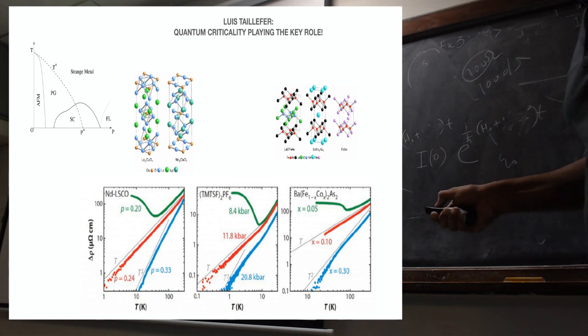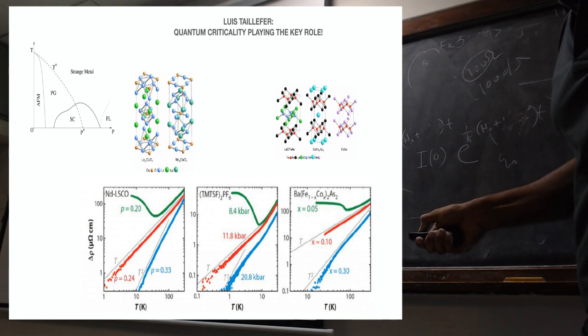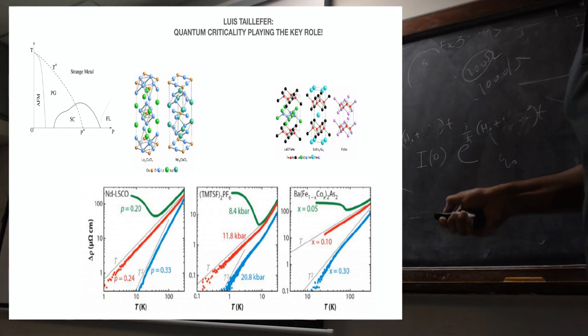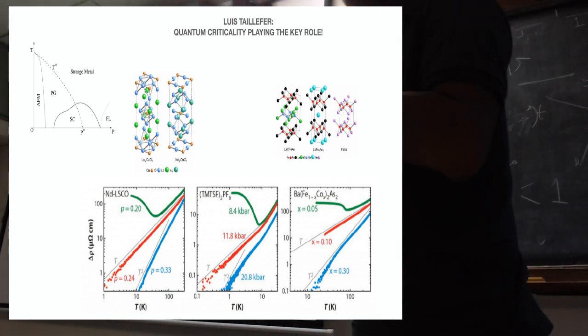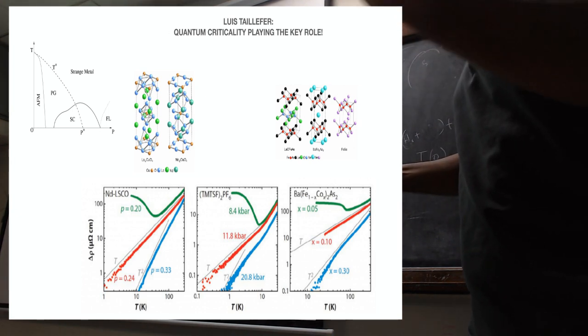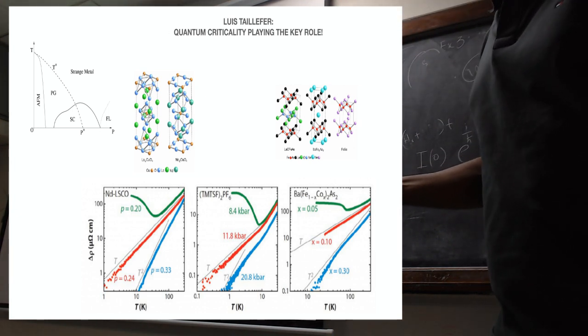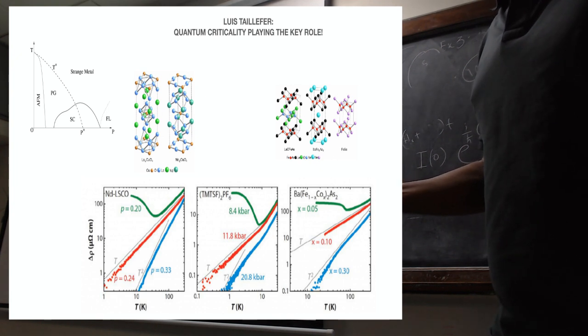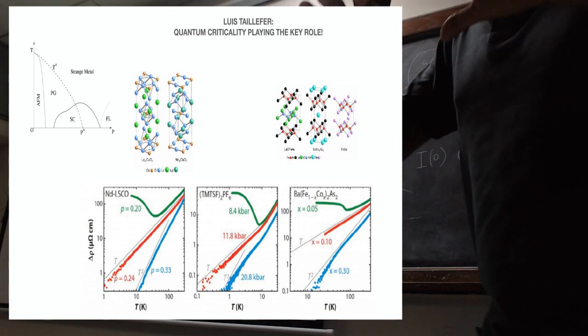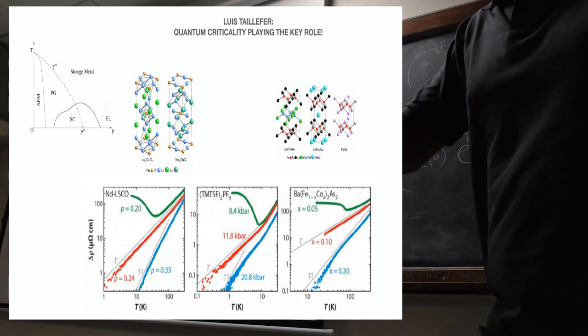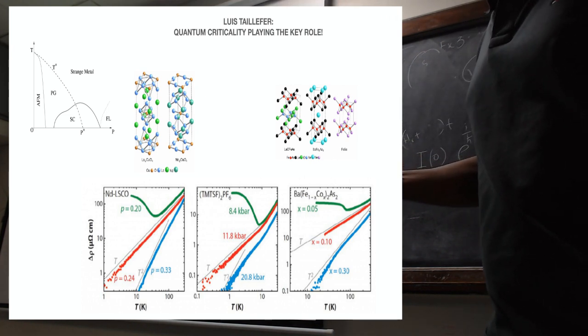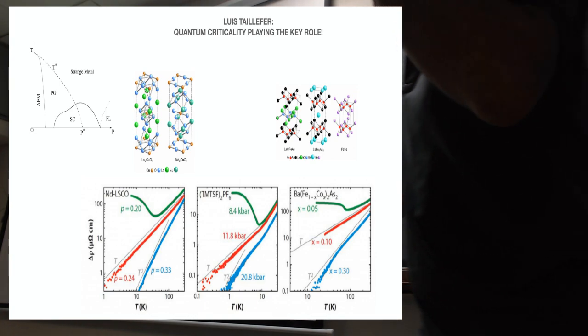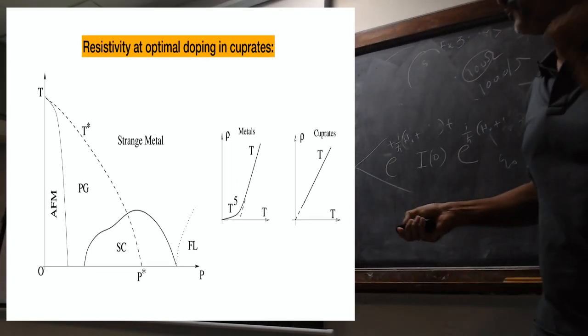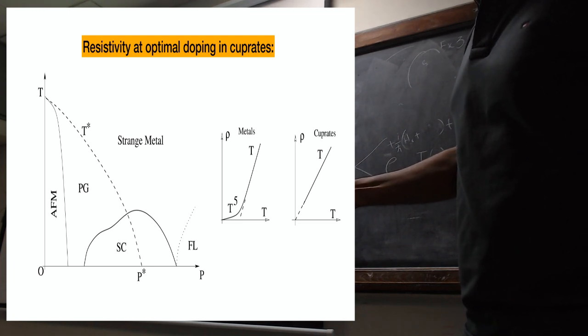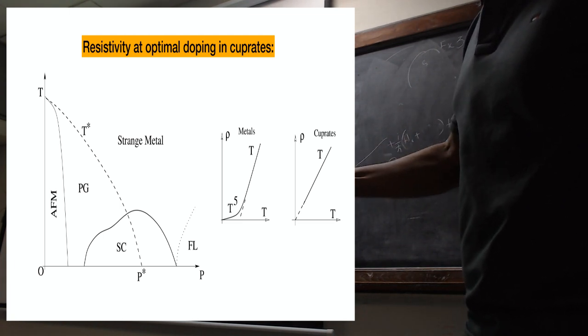This is for cuprates, it is T linear at that doping point, the quantum critical point. Then there are organic materials, with organic molecules and quasi-linear chains, which become T linear at a particular critical pressure. There are also heavy fermion systems, where you have a Kondo lattice: conduction electrons, localized electrons, and a Kondo coupling. At the critical doping, the resistivity becomes T linear too. So at one particular point, which is called the quantum critical point. Why quantum critical? Because this critical point is at zero temperature.